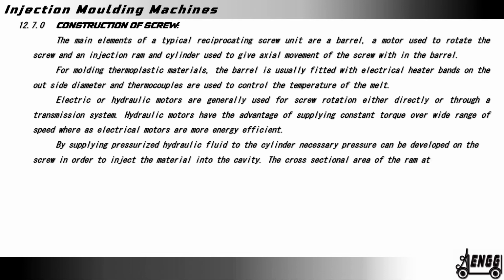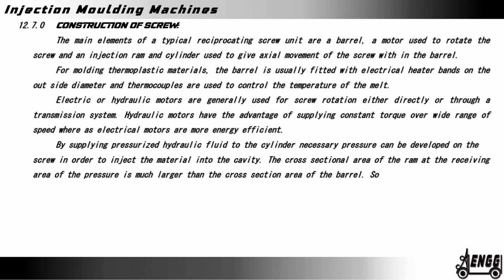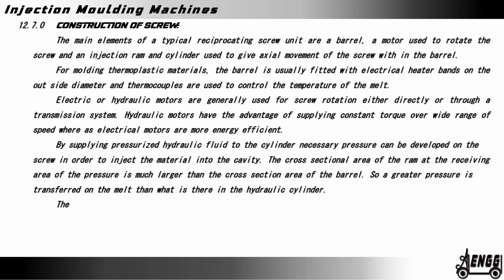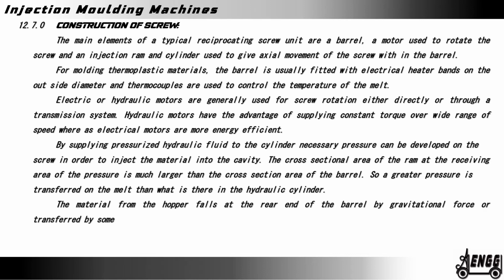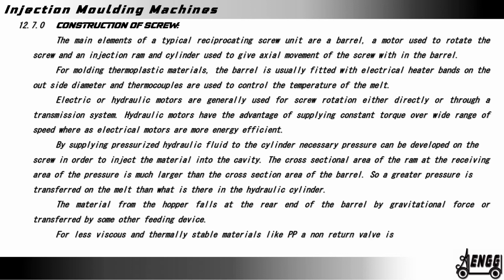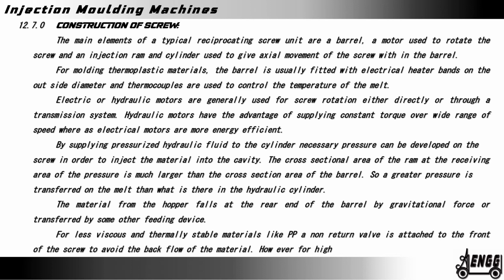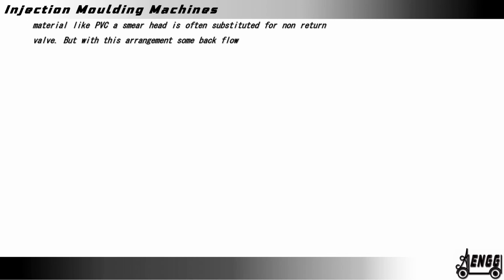The cross-sectional area of the ram at the receiving area of the pressure is much larger than the cross-sectional area of the barrel, so a greater pressure is transferred to the melt than what is there in the hydraulic cylinder. The material from the hopper falls at the rear end of the barrel by gravitational force or is transferred by some other feeding device. For less viscous and thermally stable materials like PP, a non-return valve is attached to the front of the screw to avoid backflow of the material. However, for highly viscous and thermally degradable material like PVC, a smear head is often substituted for the non-return valve. But with this arrangement, some backflow may occur, which may be minimized by reduction of flow area.